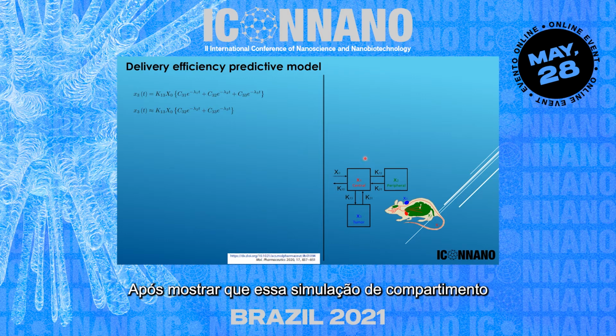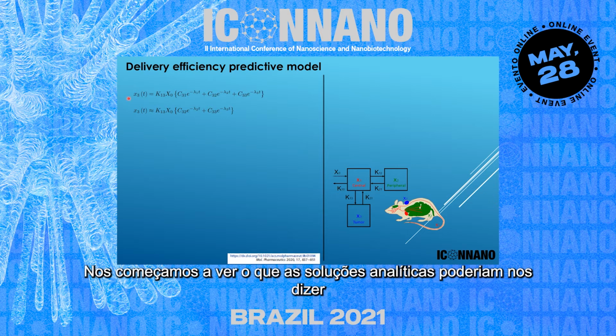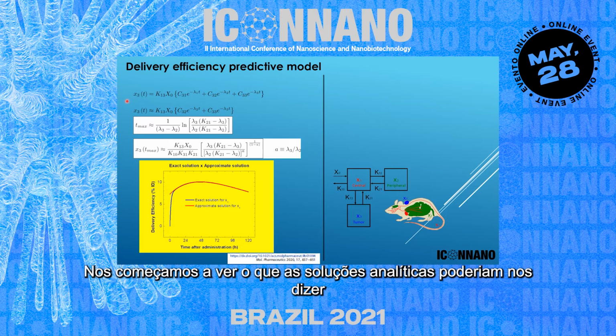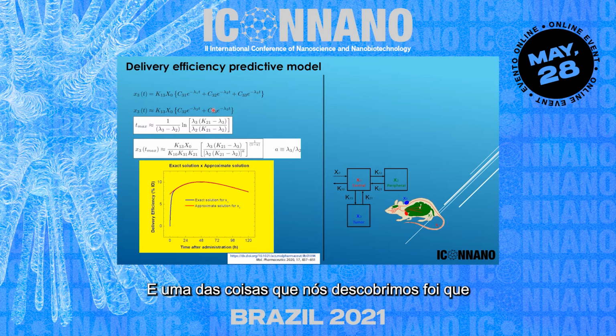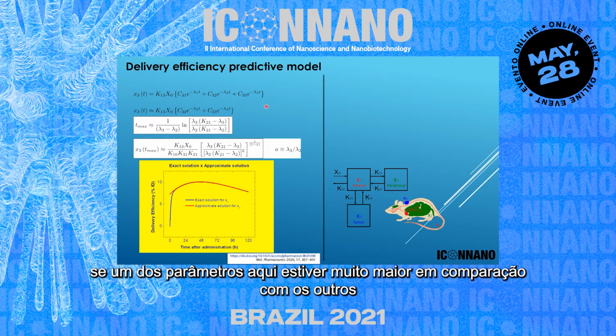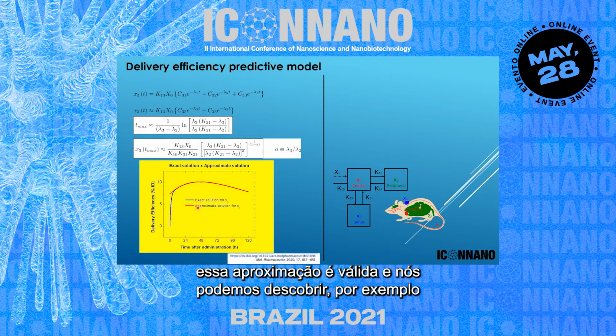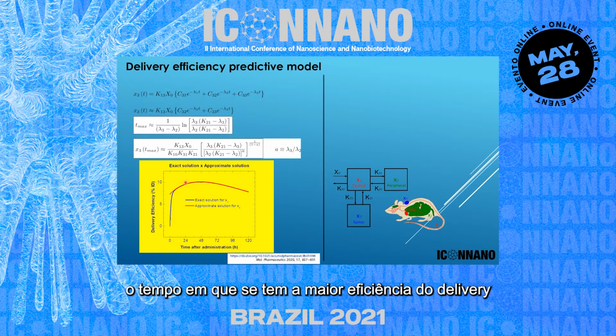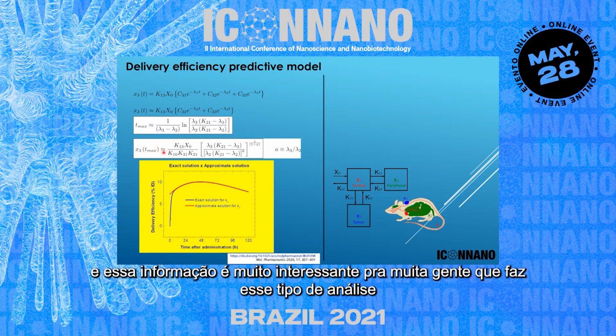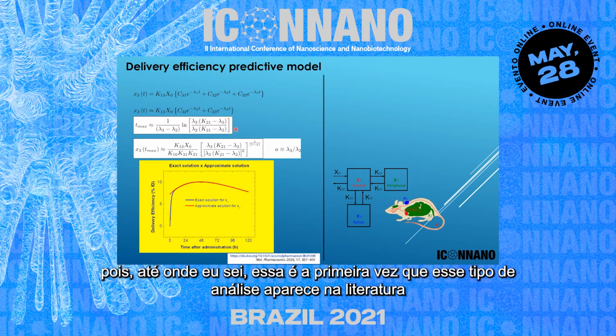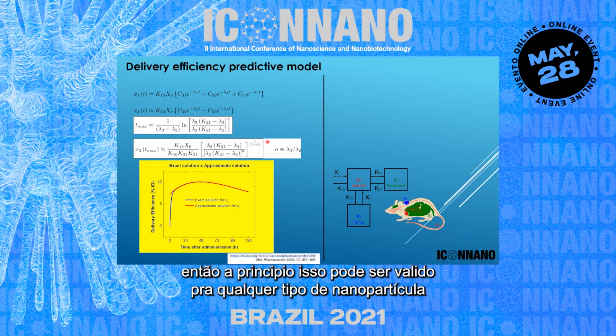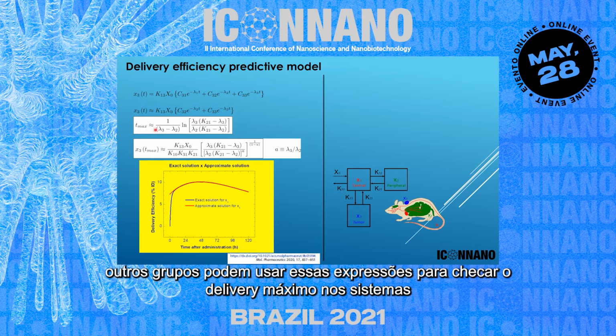Well, after showing that this three-compartment model, the numerical simulations, were equivalent to our analytical solutions, we were able to start to see what the analytical solutions can tell us. And one of the things that we found out was that if one of the parameters here is very high in comparison with the others, this approximation is valid, and we can find out, for instance, the time at which you will have the highest delivery efficiency. And this information is very interesting for several people doing this type of pharmacokinetics, because as far as I know, this is the first time that this appears in the literature, correlating those parameters here. So in principle, this could be valid for any type of nanoparticle. Other groups could use these expressions to check the maximum delivery in various systems.